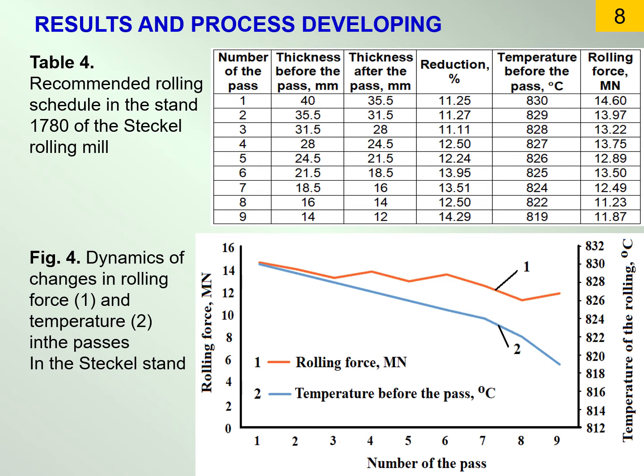Rolling in the Steckel stand should be at a temperature of 825 to 835 Celsius degrees, i.e. below the temperature of complete inhibition of austenite recrystallization, and end at a temperature of not less than 810 Celsius degrees. During the implementation of the described temperature strain parameters, during finish rolling, austenitic grains are elongated, the boundaries of which are fixed by niobium, carbon and nitrogen phases released during rolling and will significantly refine the inherited ferrite grain. The recommended temperature deformation mode of rolling on passes in a stand 1780 is given in Table 4. Changes in temperature and rolling force in the passes in the Steckel stands are shown in Figure 4.